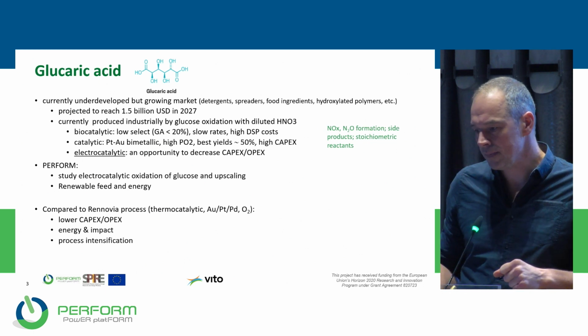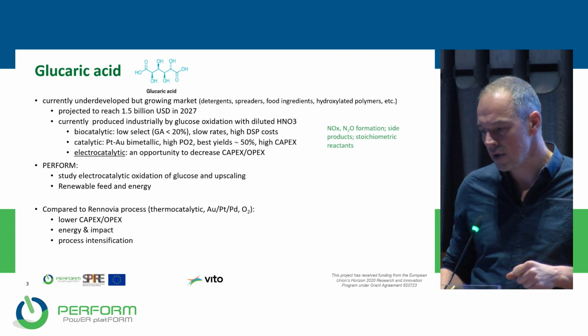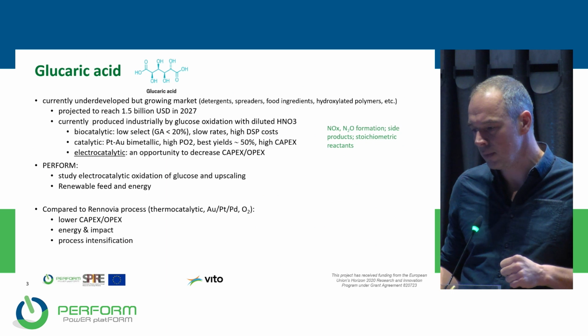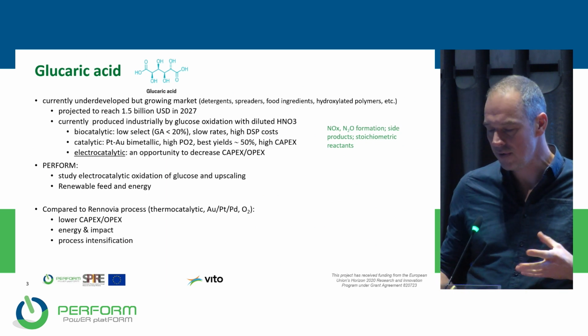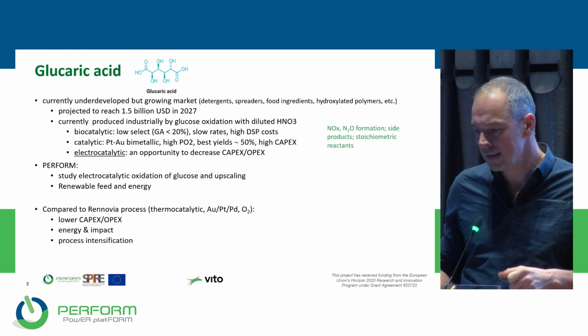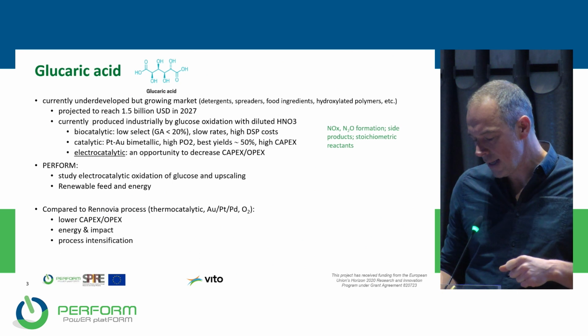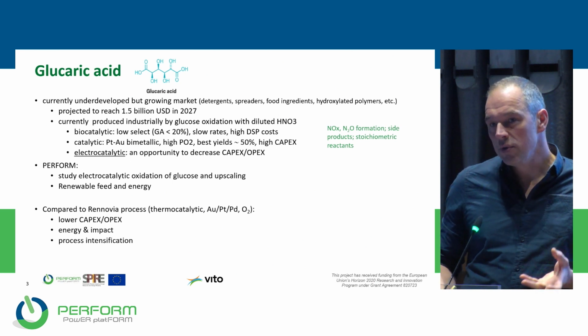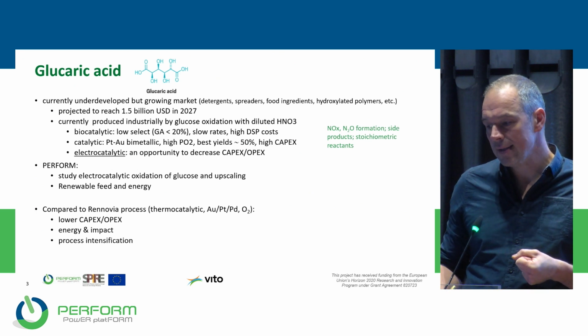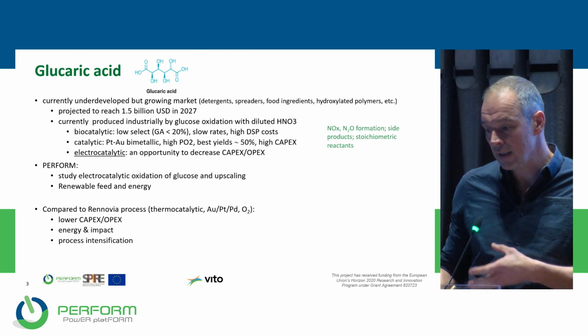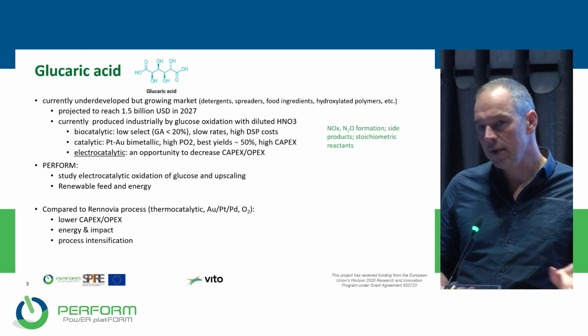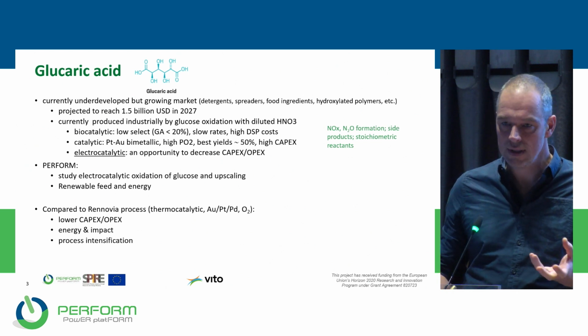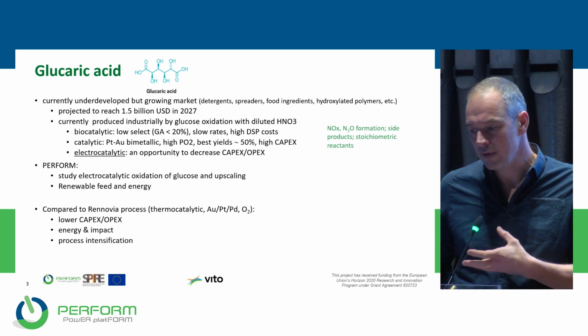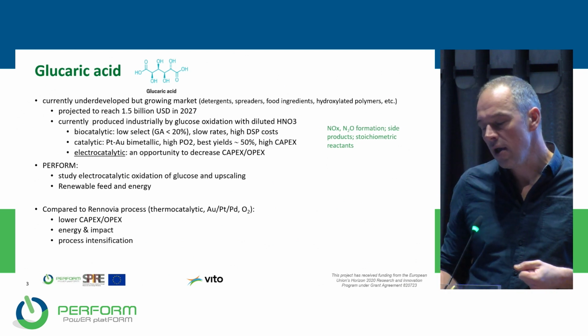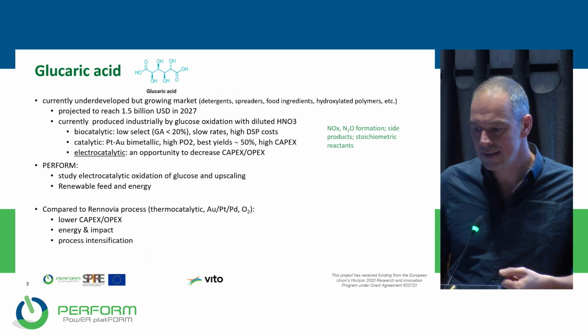But there are also some other production methods, for example, with gold, platinum, or bimetallic catalysts with very high partial oxygen pressure, but even then the yields are quite disappointing. So in PERFORM, we would like to establish a route from glucose to glucaric acid and to study this also in an upscaled version using basically renewable energy and a renewable feed. So the glucose is not to come from a feed or food-based source, but actually from, for example, cellulosic biomass, which is then converted into glucose monomers.